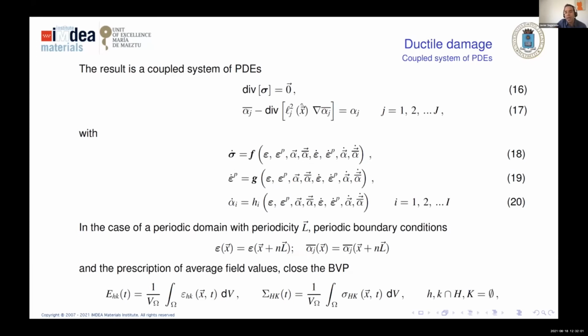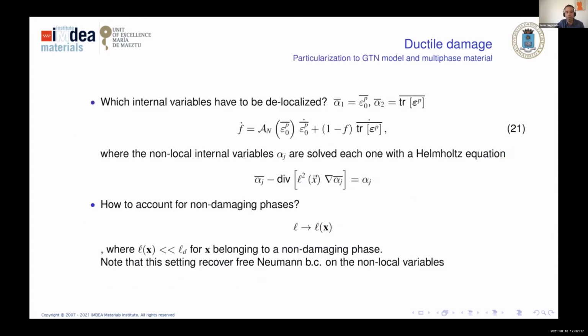So we have to solve a coupled system of PDEs: the equilibrium equation, in which sigma depends non-linearly on the non-local variable, and the Helmholtz equation that delocalizes the value of the internal variable. Which internal variables do we delocalize in Gurson? Instead of delocalizing the volume fraction of porosity, we delocalize the volumetric plastic strain and the equivalent plastic strain.